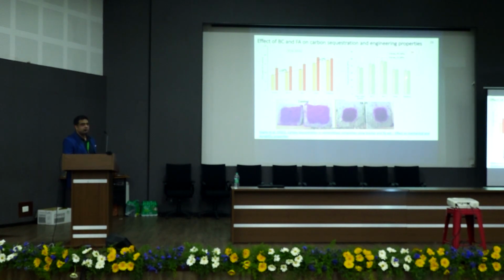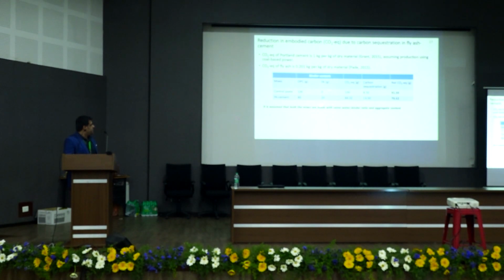What was very interesting is that if you take control and you spray phenolphthalein to find out the carbonation depth, in case of control, it's only about 3 to 4 millimeter from the edge of the specimen. When we have higher dilution, that means more fly ash, then the CO2 diffusion increases, and therefore you have higher carbonation depth, which actually means you can store higher volume of CO2 in the form of carbonate minerals in this kind of mix, right? So in terms of embodied carbon, if you combine how much CO2 reduction you have from replacing cement and how much CO2 storage can be facilitated, about 20 to 25% of embodied carbon can be reduced depending on the kind of supplementary admixture that you are using.